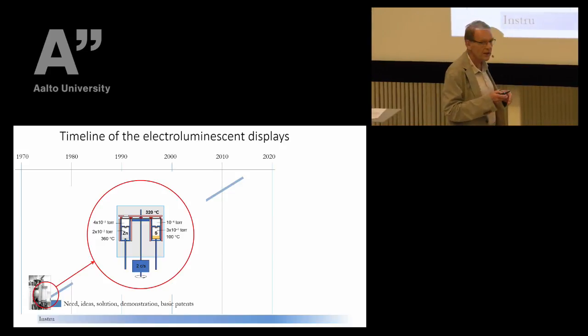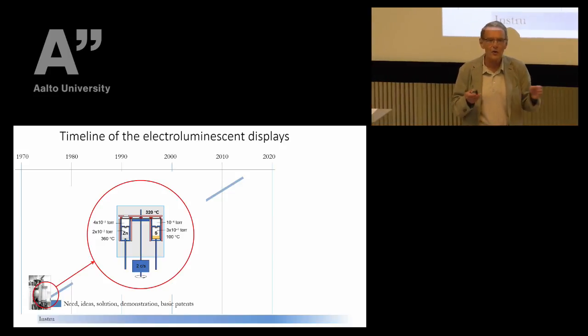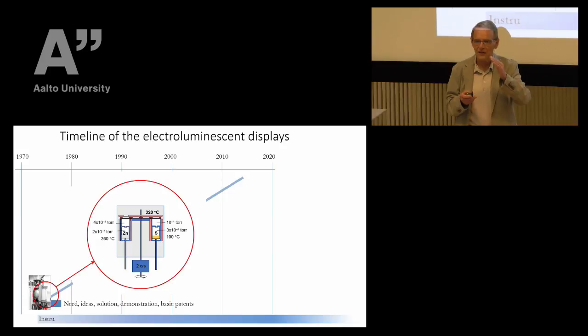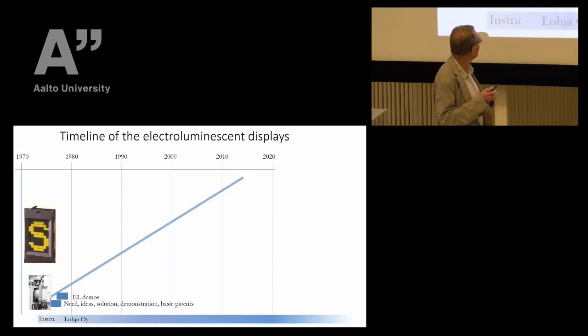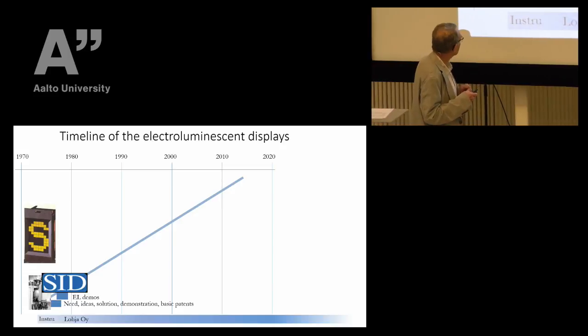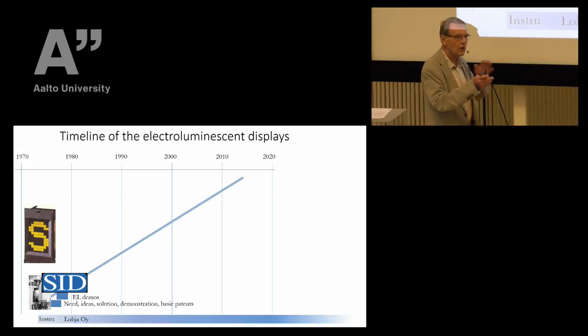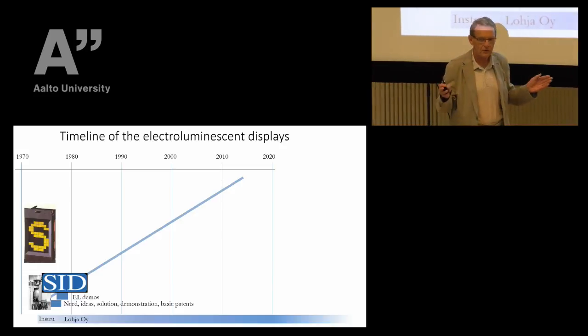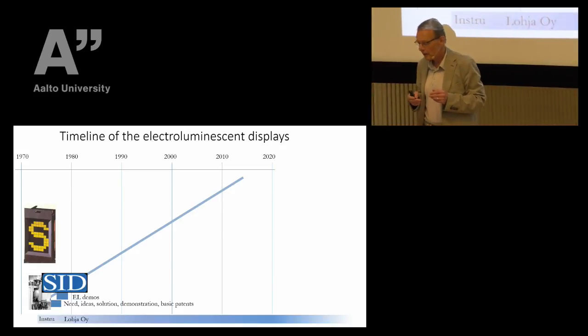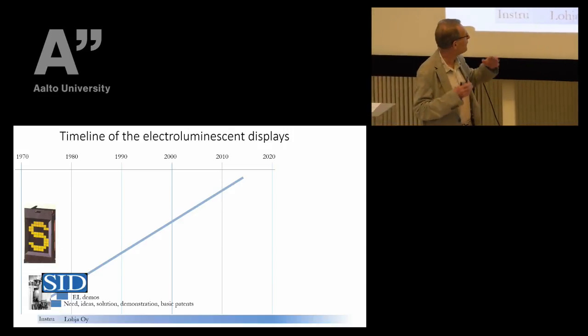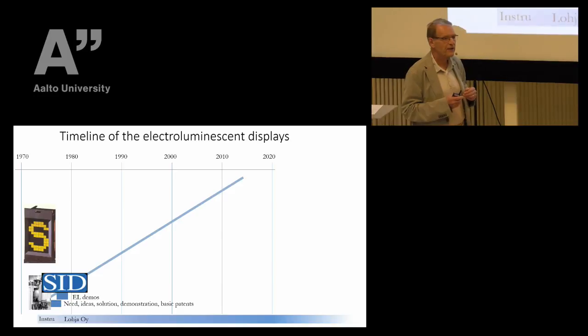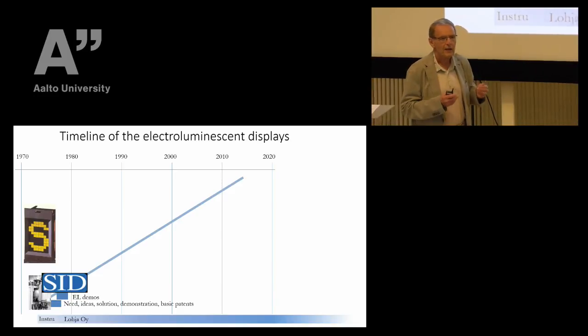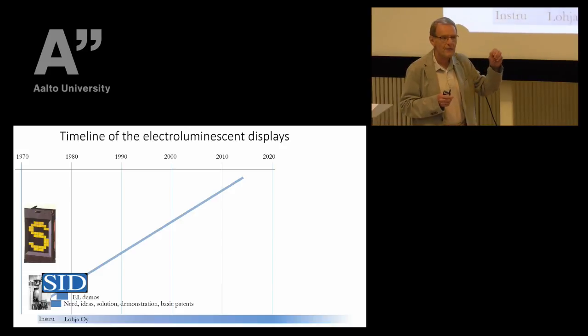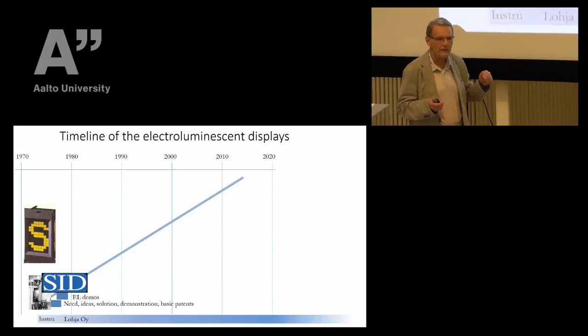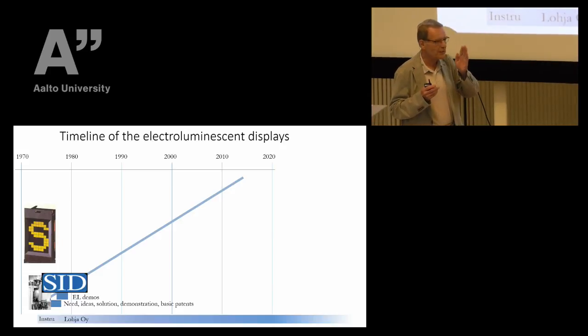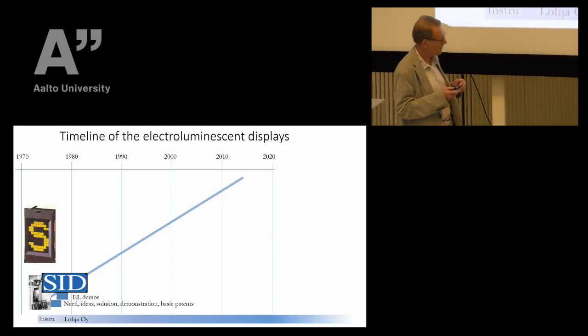And as I tell you, my disappointment was that it didn't make a full atomic layer. But the nice thing is that it made the saturation. And that's why we got ahead. It still needed a couple of years to refine the machinery. We had to make everything from the beginning, because there was no technology for fast switching of thousands of reaction cycles. And fast switching means that we have to switch chemicals which are aggressive, and the switching time must be less than a second in order to get acceptable speeds.